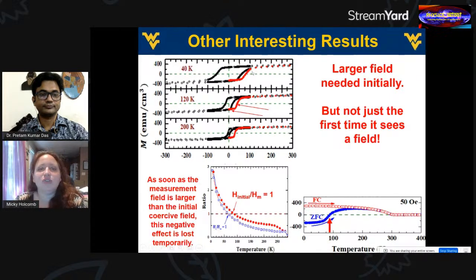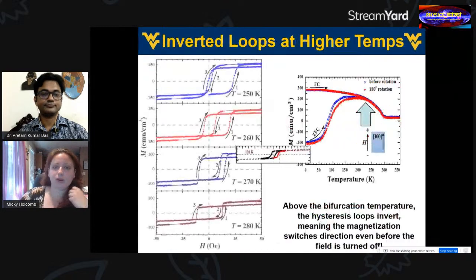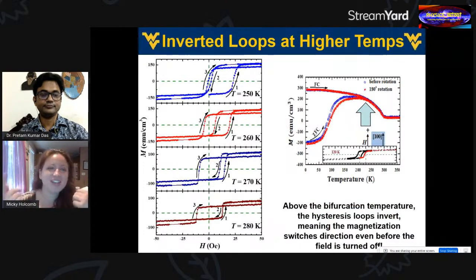If, on the other hand, you saturate it with a field and you just cycle back and forth over and over again, then yes, you're fine with the black curves in the hysteresis loops. But if you let it sit, it's going to relax back to needing this larger field again. All right. Some more interesting things.